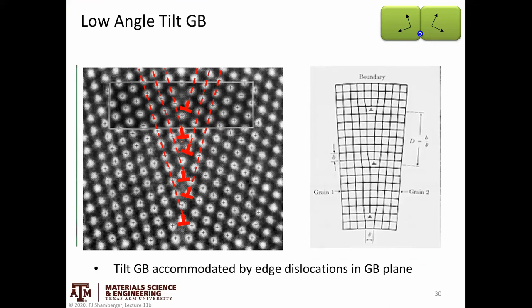The next term is a low angle boundary — this happens to be a low angle tilt grain boundary, but we could have other kinds of low angle boundaries. Low angle means that the angle of opening between the orientation on the right-hand side and the left-hand side is small — theta is a very small number. Low angle grain boundaries are special for a couple of reasons: they generally have very low energy, because there's a large portion of the interface that doesn't seem very perturbed. In fact, we can describe a low angle tilt grain boundary as an array of evenly spaced dislocations.